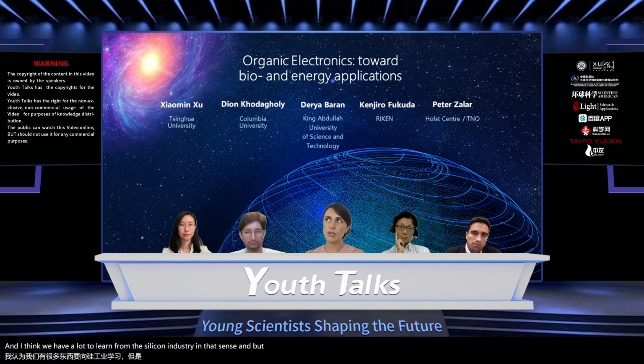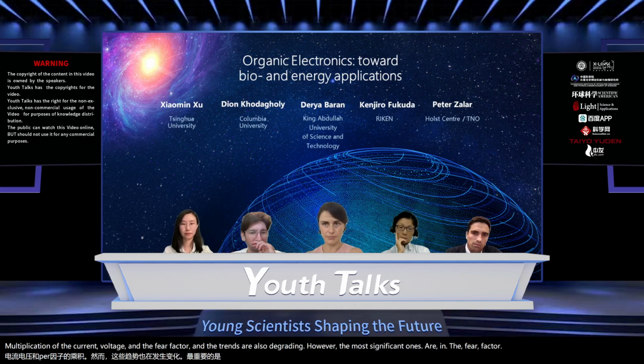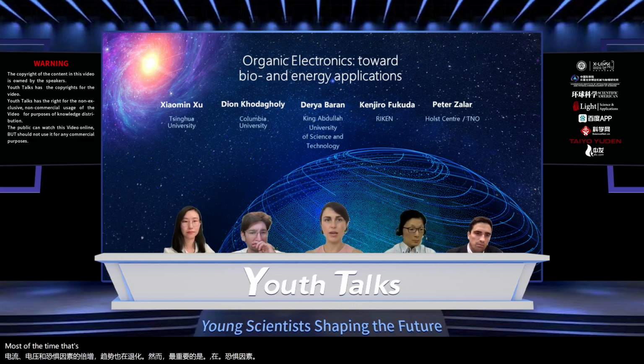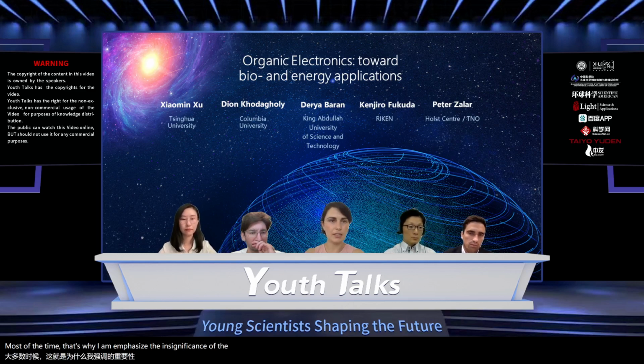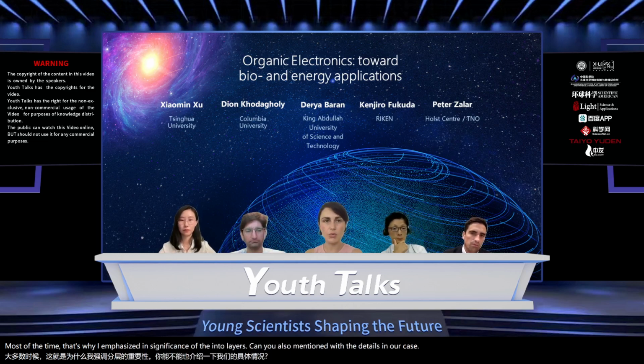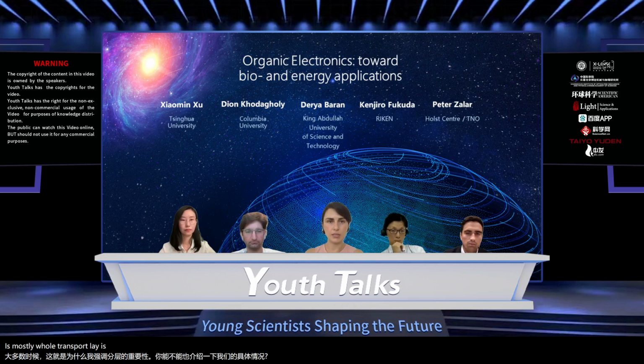But coming back to your question, because the PCE is the multiplication of the current, voltage and the fill factor, the trends are also degrading. However, the most significant ones are in the fill factor most of the time. That's why I emphasize the significance of the interlayers. Kenjiro also mentioned the ETLs. In our case, it's mostly the hole transport layer. Is something happening there?